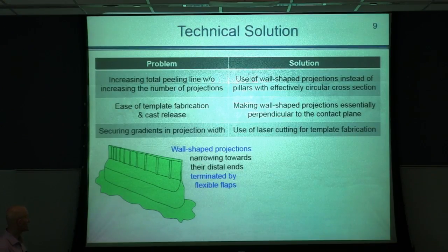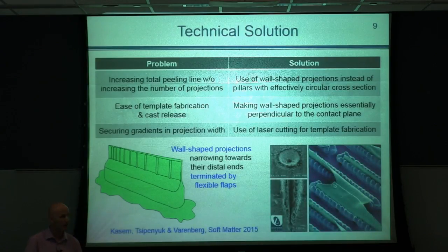So, wall-shaped projections that narrow towards their distal end and have flexible flaps that can deform easily when they come in contact with the counterface. So we found a British company, a laser company, that was able to create tiny openings within larger patterns. These are two examples: a hole inside a hole and a through slot within a blind slot. And this is an example of one of the first trials of the projection of the surface structure that we created based on this principle.